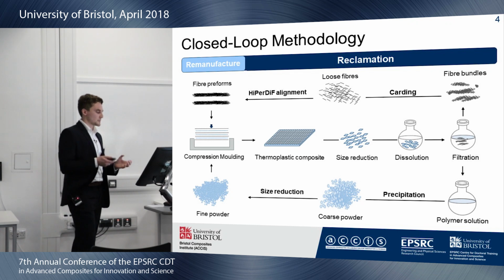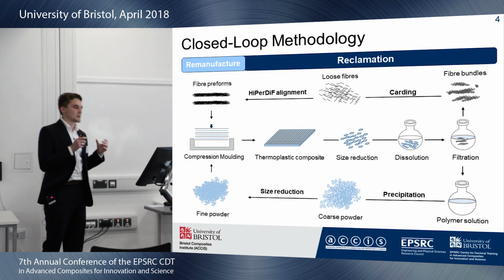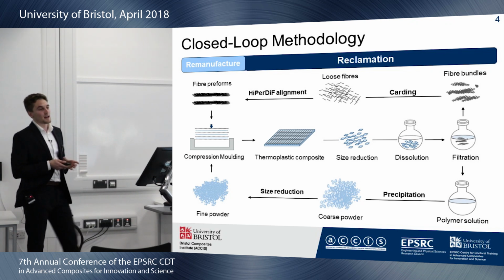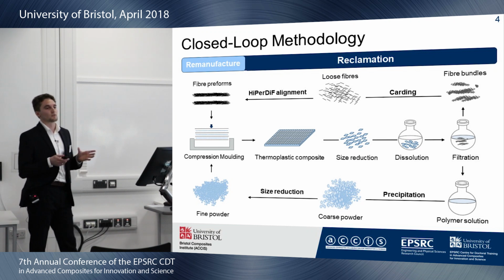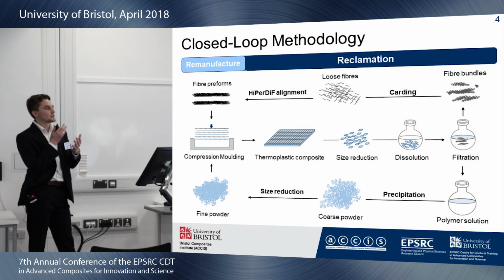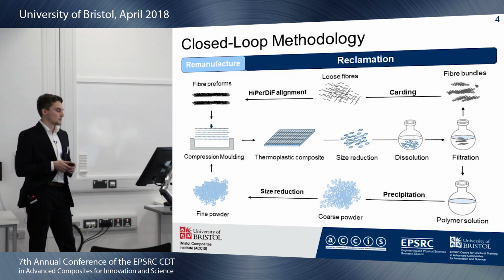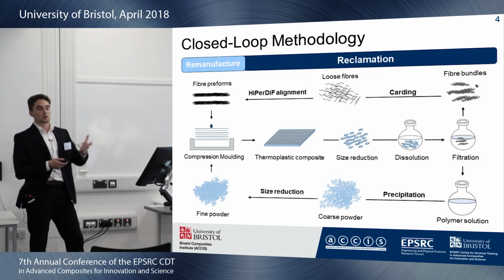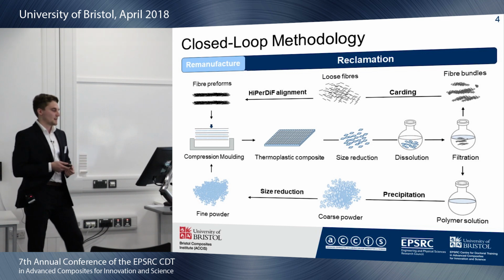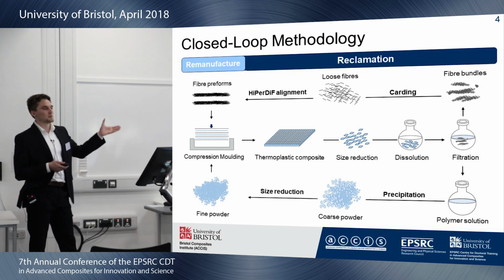So the process that I developed is basically you take a thermoplastic composite, you shred that, and then you dissolve it in non-hazardous solvents. We're using thermoplastics so that we can separate those temporary intermolecular bonds in between the polymer chains instead of breaking the intramolecular bonds which cause chain scission and loss of properties. So as we dissolve that thermoplastic into the solution, we have fibres, the reinforcement fibres, dispersed within that. We filter those out and then we card them and align them using the HiPerDiF method.